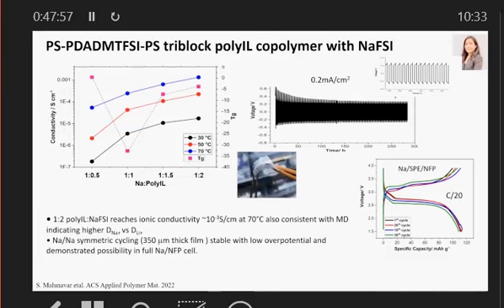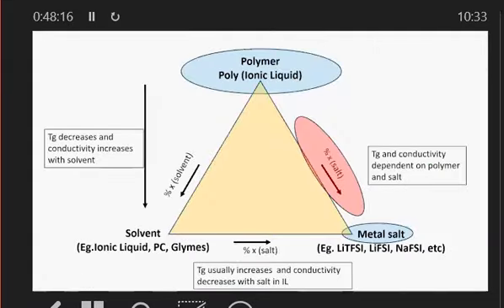At the time, all we've done so far with this system is put it into an NFP cell, just to show that it did actually operate as a battery electrolyte, but we've got a long way to go still before we optimize the system, obviously. It's a very thick film, 350 microns, that will impact this behavior in the full battery and also in the symmetric cycling. So we've got a long way to go still to optimize this, but I think it's fair to come back to my first slide and say there is a lot of space to play in these systems for solid state batteries, whether it's lithium, sodium, or any other metal system.